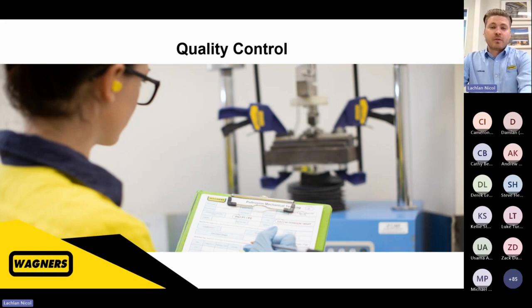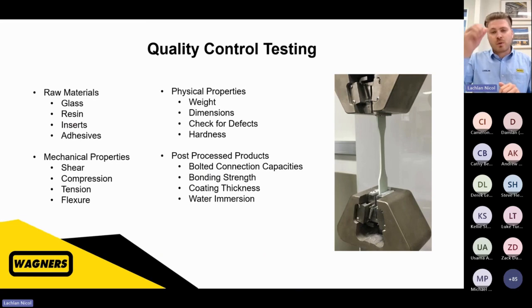Part of the key point of difference as well for us is being ISO 9001 accredited. So we have a very stringent quality control program that includes raw materials, goods inwards, essentially, our glass, resin, inserts, adhesives, what have you, mechanical properties of our actual raw material, our raw pultrusion, physical properties, weight, dimensional checks, what have you, and then also our post-process, so our inserted material, our bonded material, our coating thickness. So checking every single process down the line to ensure what the asset owner gets at the end of the day is as designed, as expected, and will last that full 100-year design life.